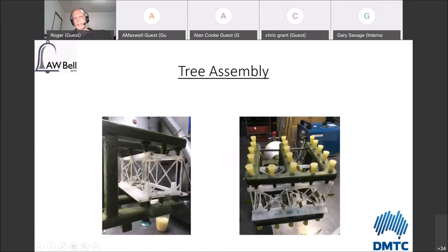On the right-hand side, you can see these are vents that are being put in. Now, the vents are there for two reasons. One is to get the wax out before you flash fire it. The other is that when you flash fire it, you've got to get lots and lots of oxygen in so that you can burn off the SLA pattern very, very quickly. There's also some small vents which you can see here on the thin sections.